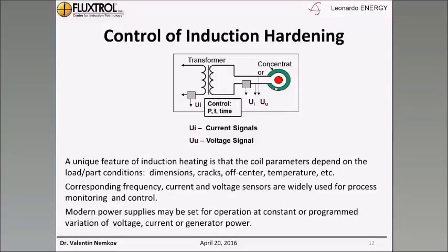Now, I mentioned the necessity of strong control of induction hardening. In addition to traditional control such as the reading of a pyrometer, we can use the unique feature of induction heating, which is the dependence of coil parameters on the load, the part conditions, dimensions, cracks, off-center, temperature, etc. For example, if you place here a wrong part with a wrong size, you can feel immediately the change in parameters, and the control system can say, oh, that's the wrong part.